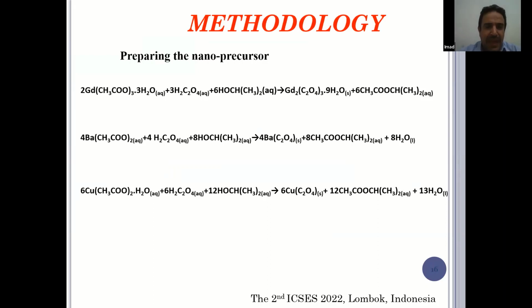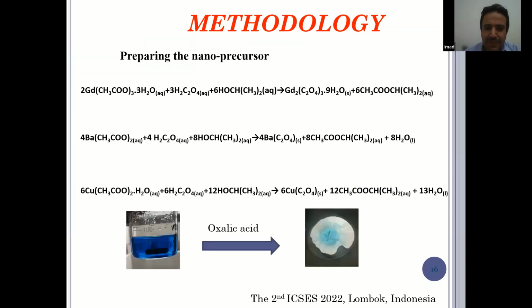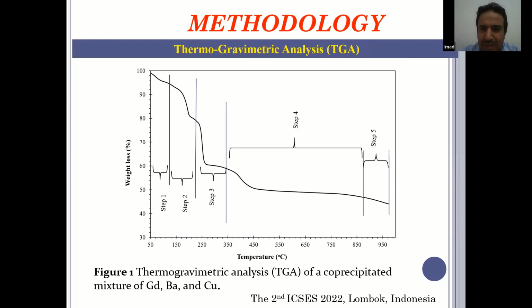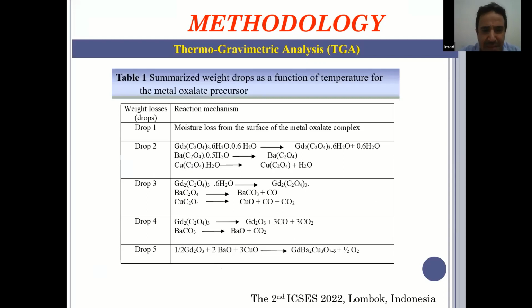After reacting the gadolinium, barium, and copper acetates with oxalic acid, we will have a highly homogenized mixture, and the precipitate will be a sky blue color. That is dried overnight, and the next day we do the thermogravimetric analysis in order to find the correct temperature for heat treatment, calcination, and sintering. As you can see here, there are 5 drops, and these drops are summarized in table 1, showing each drop and the chemical reaction occurring at that step.